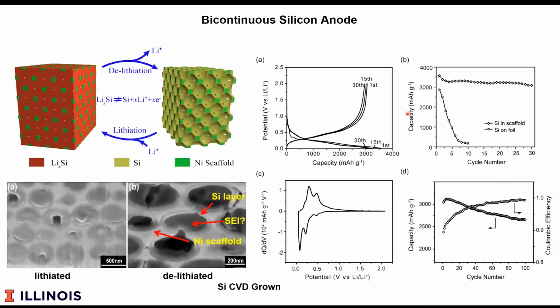Now in a system, if you take a foil of silicon, it simply fails as it expands; it fragments. If you take a scaffold, on the other hand, because it can breathe in and out, it's able to retain a significant fraction of its capacity. I'll primarily show you work on silicon grown by CVD, but I'll also mention some work on electrochemically grown silicon, probably more practical for real application.